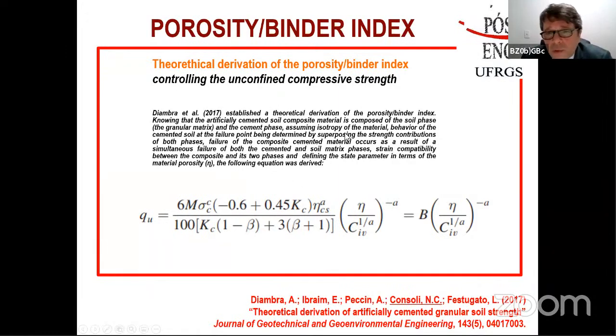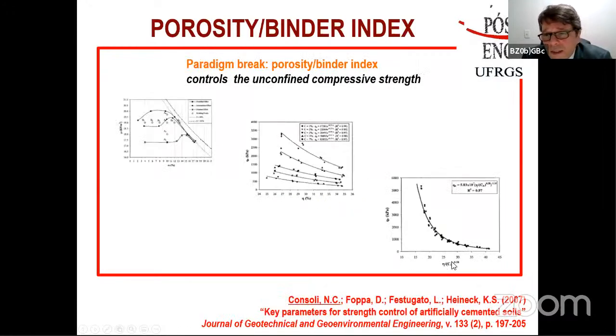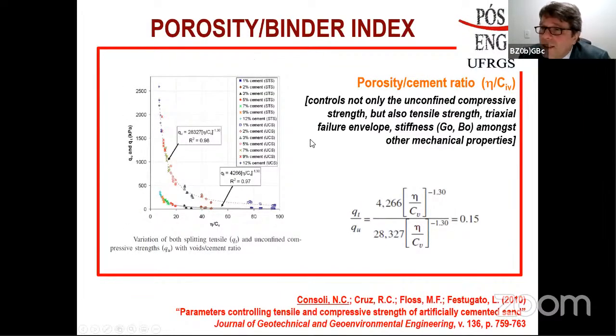And so we have been able to develop analytical solutions showing that this parameter really controls the strength, but in a first analysis, it controls the unconfined compressive strength. But then we have shown in the lab and also from the analytical viewpoint that it controls also the tensile strength. So this porosity cement ratio or porosity cement index, whatever is the name that you see, it controls completely. Here we have the results of different amounts of cement and different densities, and all of them fit in a unique curve for unconfined compressive strength. And here we have another curve for tensile strength.